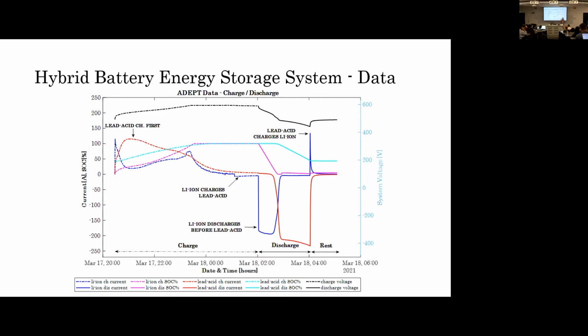Usually if you buy an inverter or a charger for your house, it's 97%. But it drops to lower values if you're charging really slowly. So what you can do is charge the system at a very high rate, so it's added from lithium ion to lead acid. Although we don't want that to happen, we can work with that.